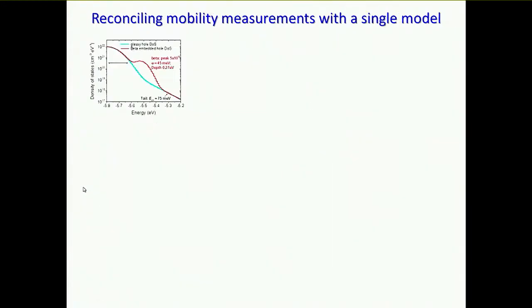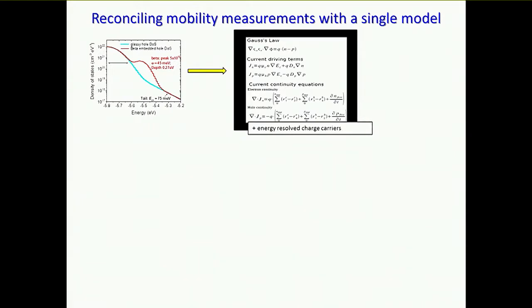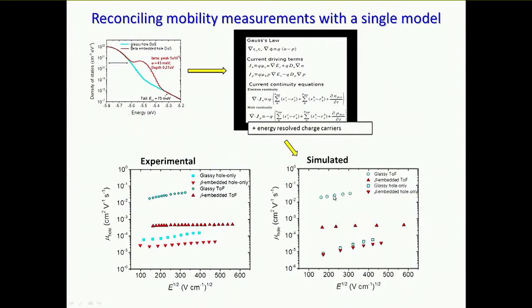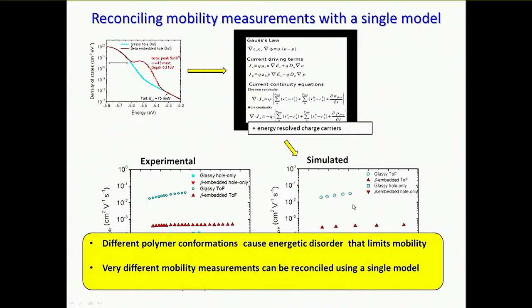So having got that, could we then make sense of the measurements? And so we then needed a model. We can't use a normal device model that models drift and diffusion, assuming quasi-thermal equilibrium, because that wouldn't be able to reproduce the transient measurements properly. We had to use something where we have that resolution, but we can also assign an energy to the charge carriers so that any time we know where they are in the density of states. And we developed such a model, and then we could apply it to simulate both the transient measurement and the steady state measurement. Doing that, we could simulate the large effect of introducing these beta phase traps on the mobility in the transient measurement, and also the much smaller effect on the steady state measurement. So both of those results that had been seen in the experiment popped out of the simulation. The simulation was able to reconcile the apparently different measurements.